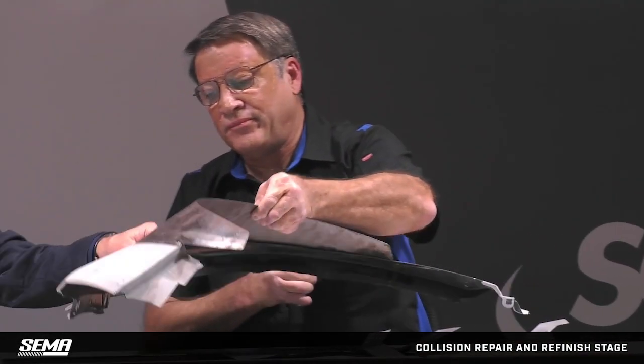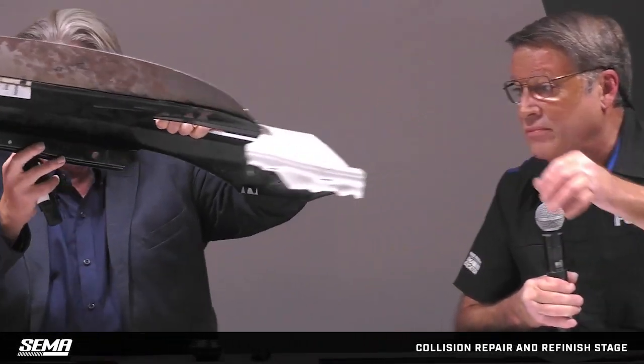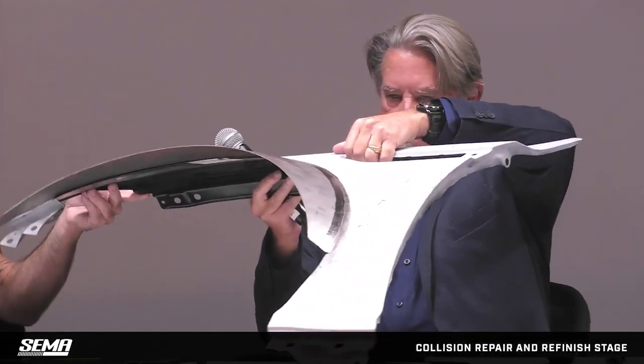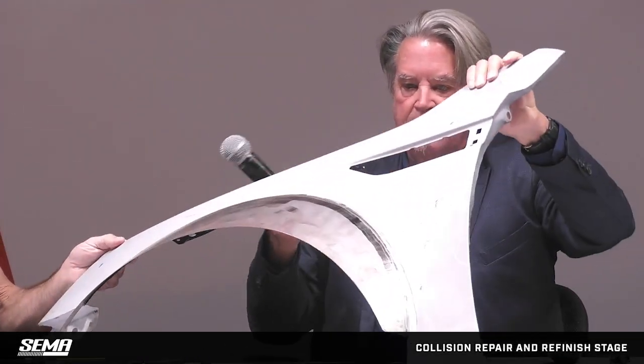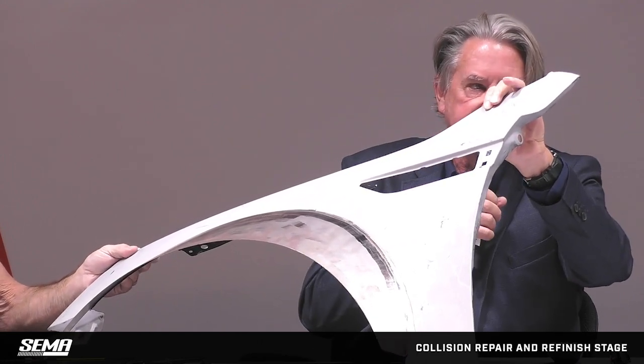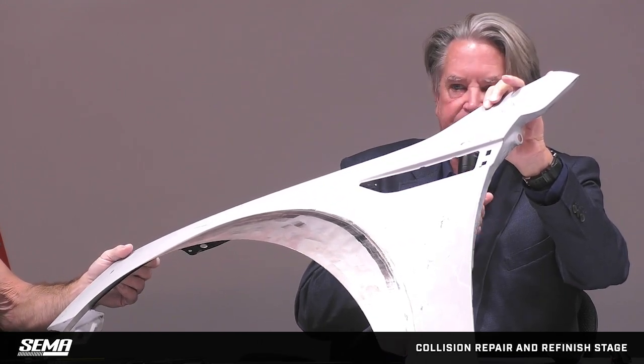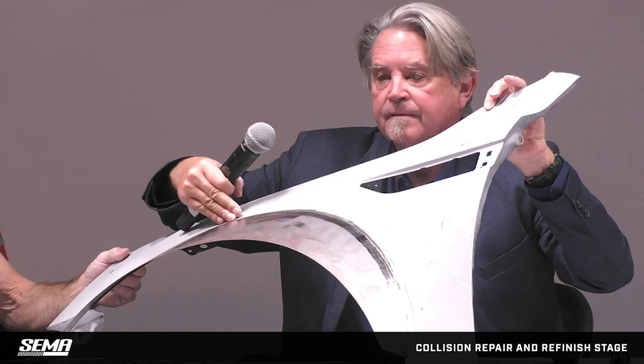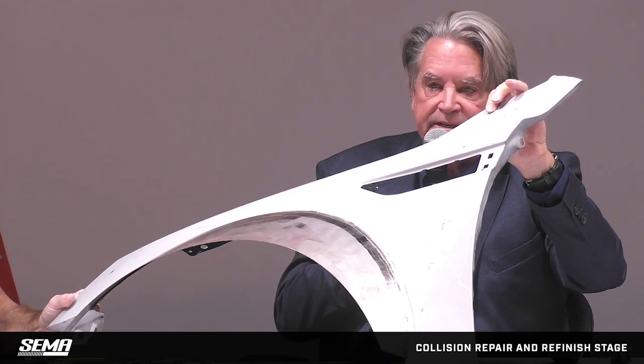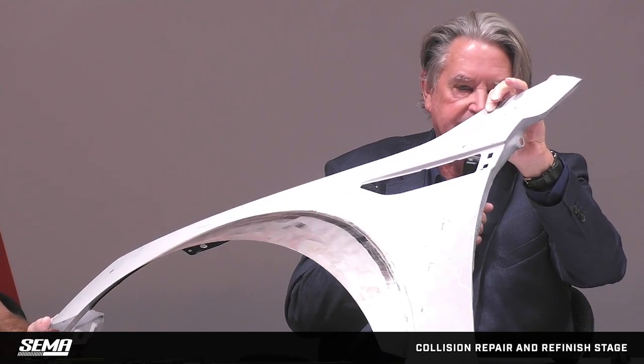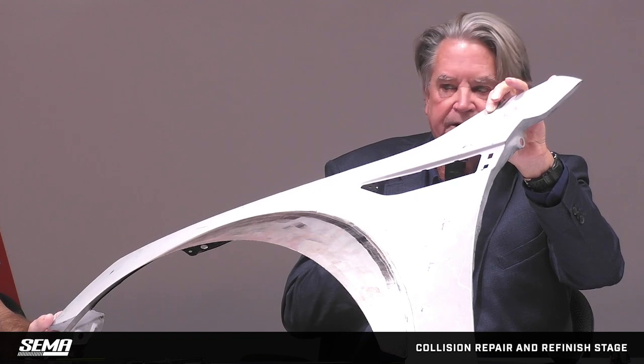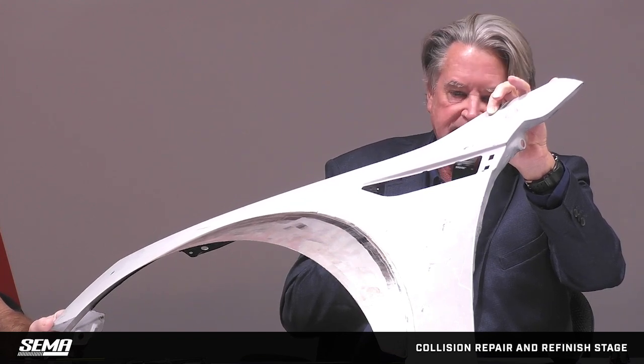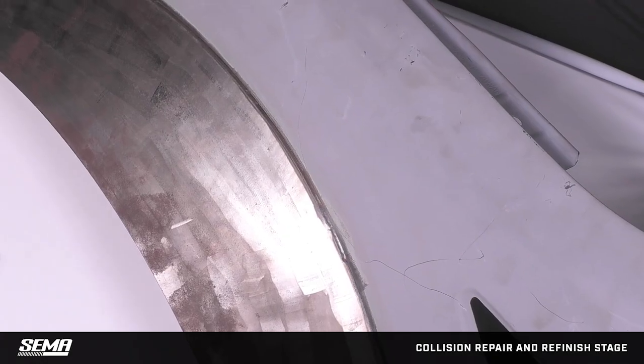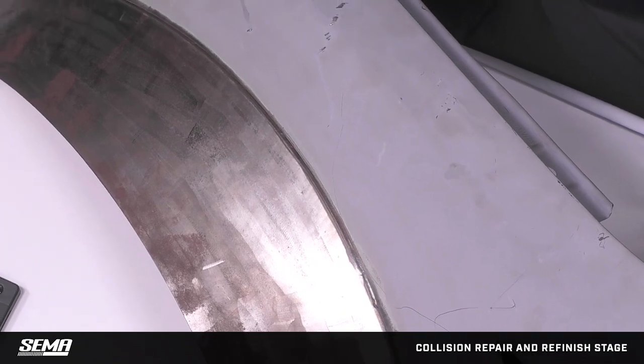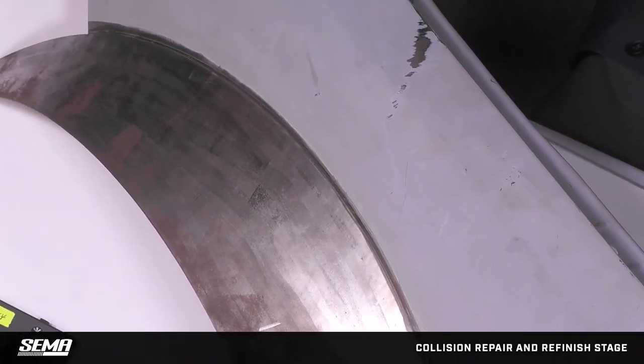Yeah. So what he had done here is he had actually used the laser itself to clean the paint off the part, and then he tacked the flares in place, and this is about it. He told me this is a 2-minute weld. He started on one side and went all across the bottom. He didn't jump around. He just welded it, and you can see there's no distortion at all.